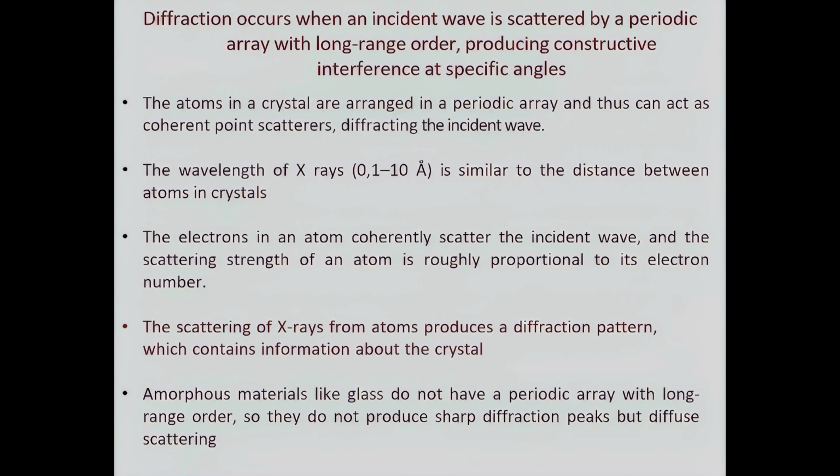Then, if this is a simple definition of diffraction, why are crystals able to do this? They are able because, as you remember, a crystal is, by definition, a periodic distribution at long range of atoms or molecules. Then the crystals satisfy this condition completely, and this is the reason why a crystal is able to perform a diffraction.